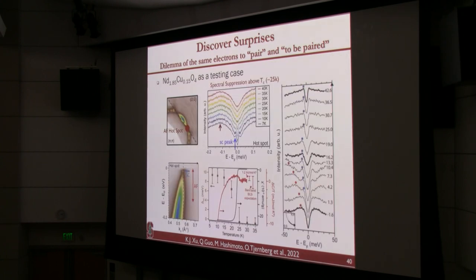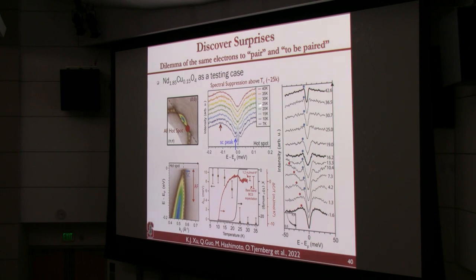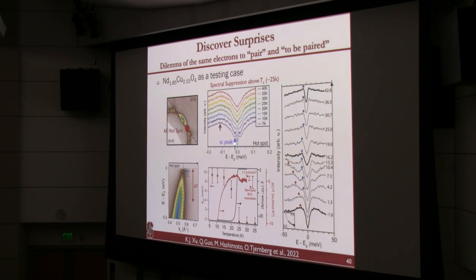Now if you take it more quantitatively, you can see here the temperature dependence. This is a material with a relatively low TC by cuprate standards, 25 Kelvin, but it's the best in electron-doped systems. And you can see that above TC, there's a very large energy scale over which the spectral weight is really suppressed. Then below TC, you also see, at a much lower energy scale, one order of magnitude lower, a superconducting peak. If you look at the temperature dependence of this peak, you can see it coincides with TC. That's the magnetization of that.